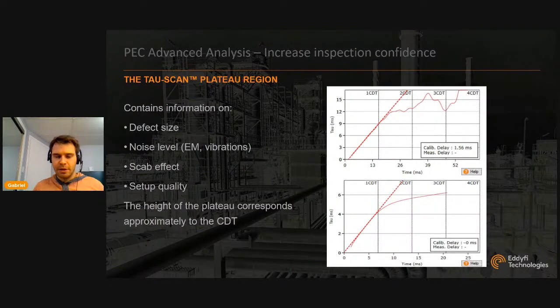The third part of the Tau-scan is the plateau. There's many use cases. We're not going to go into too much detail in all of them. We don't have that much time today, but that's going to provide you information on defect size. As I said, on defects larger than the probe averaging area, you're going to get a single plateau. That corresponds more or less to the CDT. So the value in milliseconds is going to correspond to the CDT. In this case, we would have just a little bit over 6 milliseconds CDT.